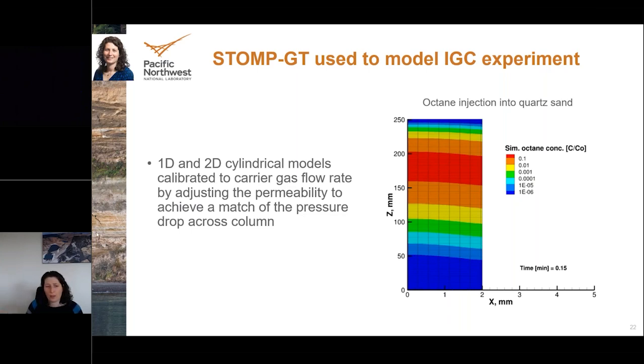The cylindrical models were calibrated to the carrier gas flow rate by adjusting the permeability of the material to achieve a match of the pressure drop across the column that you see experimentally in lab.